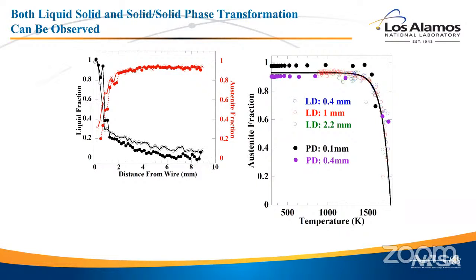Turns out the temperature at which austenite transforms to ferrite is independent of the rate over that 1 order of magnitude. Now, if you changed it to 1 million per second, which is powder bed fusion, or a degree an hour, which is casting, that conclusion might change. But over this relatively small range of cooling rates, the temperature at which ferrite transforms to austenite is independent of the rate. And it's fit by an exponential equation.